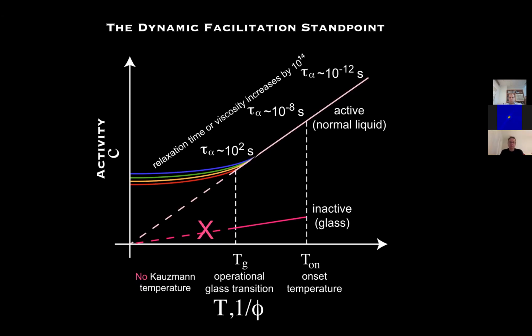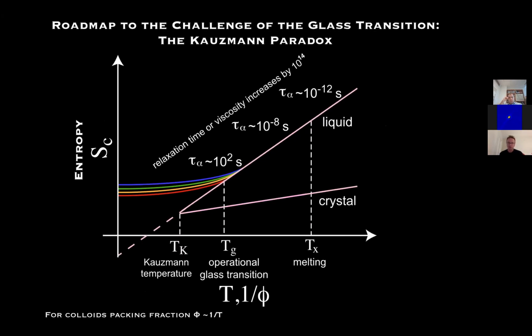So if I now go back to my dynamic facilitation picture, this is not right, because the original dynamic facilitation picture said nothing happens until you get to a temperature equals 0. Well, we've shown that that's not right, because actually there is a finite temperature at which the dynamical inactive phase has a lower critical point with the active phase.